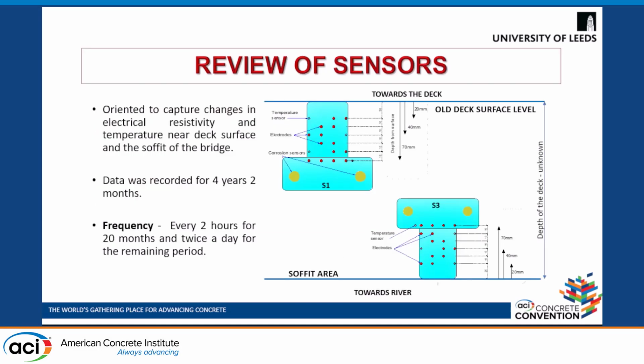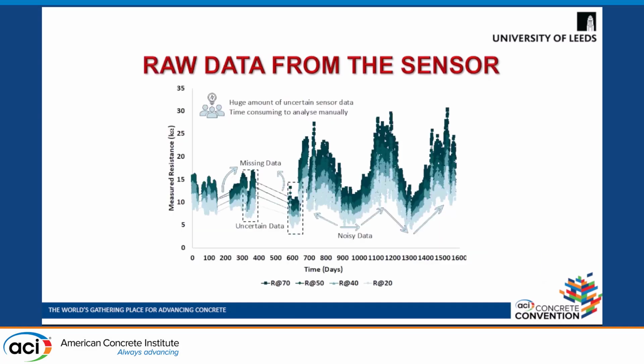These 2 sensors are oriented in such a way to capture the changes in electrical resistivity and temperature near the deck surface and the soffit of the bridge. The data was recorded for over 4 years, and it was recorded every 2 hours for 20 months, and thereafter, it was recorded twice a day for the remaining period. This is the raw data that was captured from the sensors, and you can see here that there was some missing information, some uncertain data, and some noisy data present.